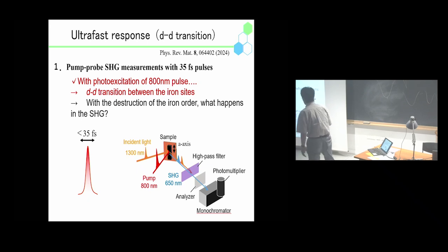Here is the experiment setup. We irradiate the crystals with the 800 nanometer light. After that, we irradiate the crystal with a 1300 nanometer probe light, and we detect the 650 nanometer SHG light by using a filter, monochromator, and photomultiplier.